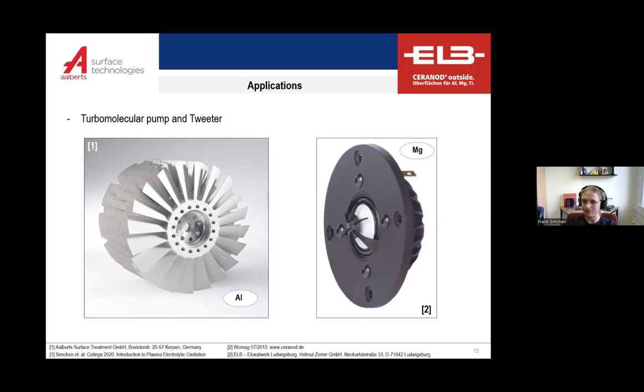And on the right side, we see a sound speaker. This is a component of high quality sound systems, which are used in expensive cars, for example. And this is made from magnesium. Magnesium is much stiffer than, for example, polymeric materials, has a better acoustic damping behavior than most other metals, and can be produced by investment casting with very thin walls. And so magnesium is here really the material of choice for such a sound tweeter. And in order to provide a decorative coating and to prevent corrosion in use, a PEO coating is applied here.